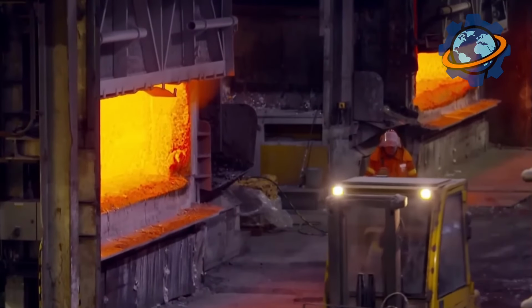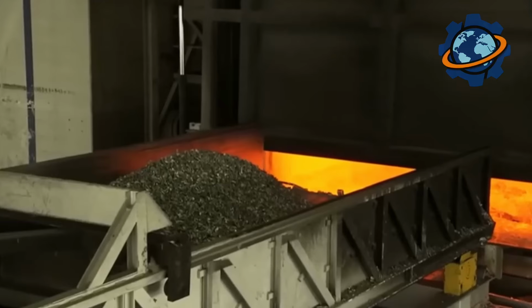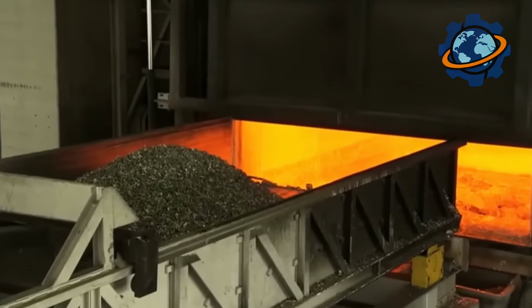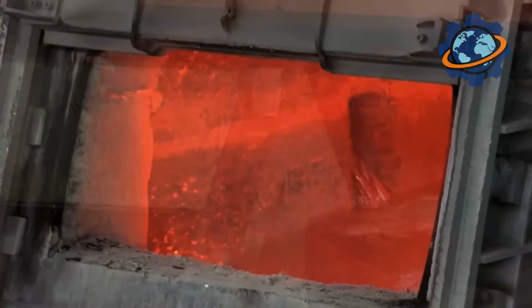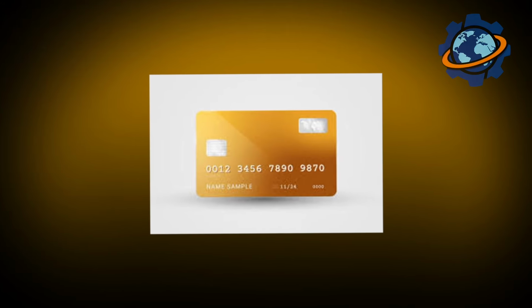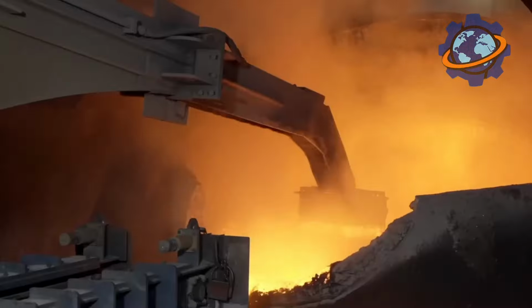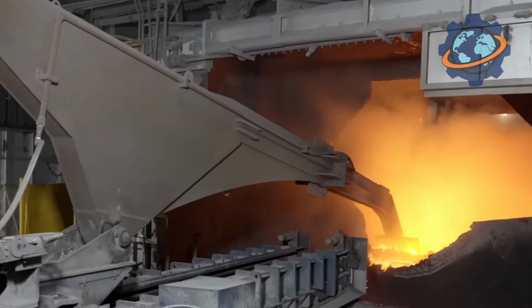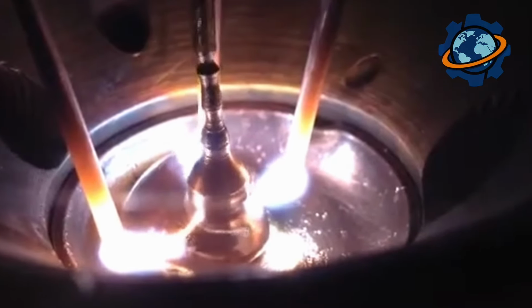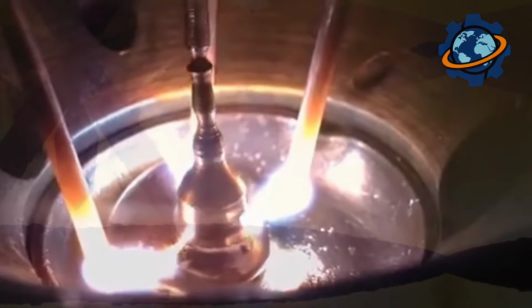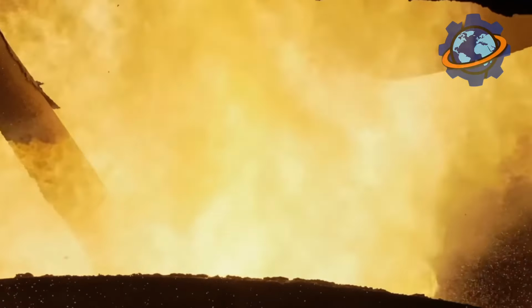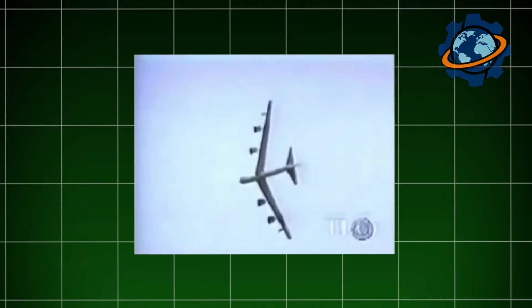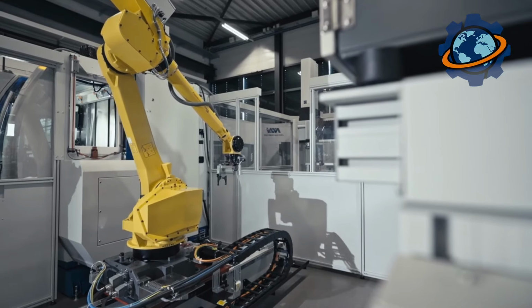These molds contain passages narrower than spaghetti strands, designed to cool blades from inside during operation. Some channels measure just 0.008 of an inch across, thinner than credit cards. Manufacturing these passages requires such precision that lasers verify every dimension. One blocked cooling hole means blade failure at 300 degrees lower temperature. That's the difference between safe flight and catastrophic engine disintegration at cruise altitude, scattering turbine fragments through fuselage like shrapnel.